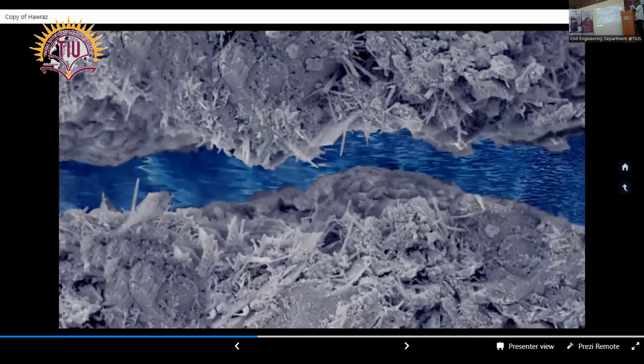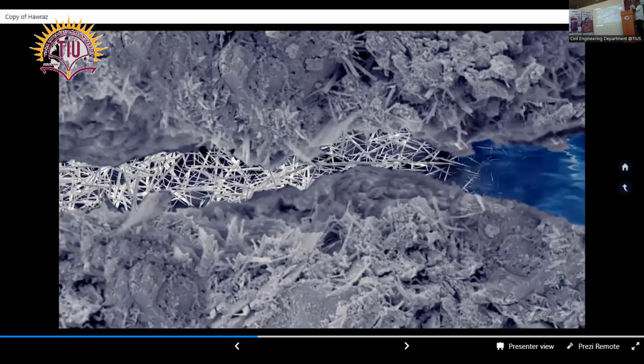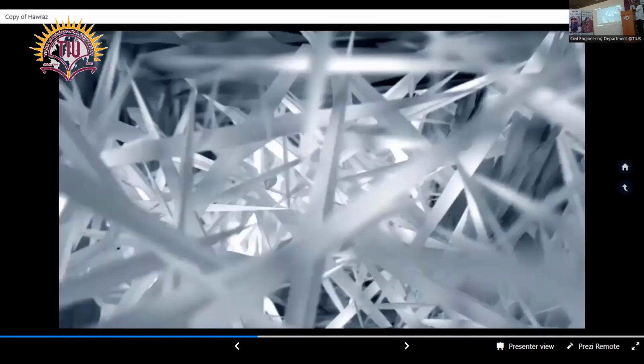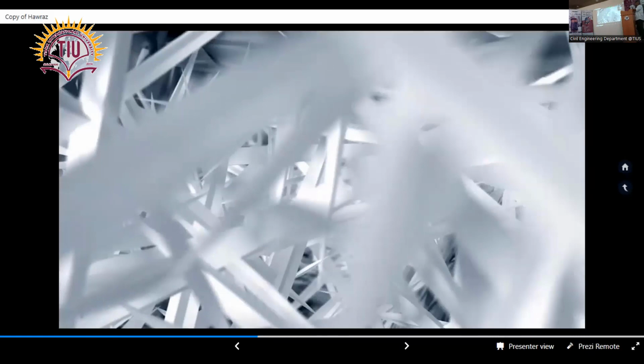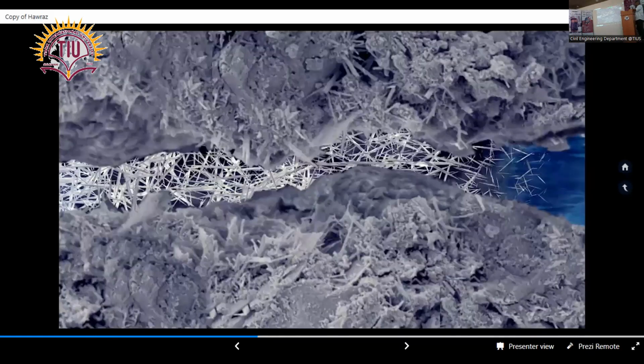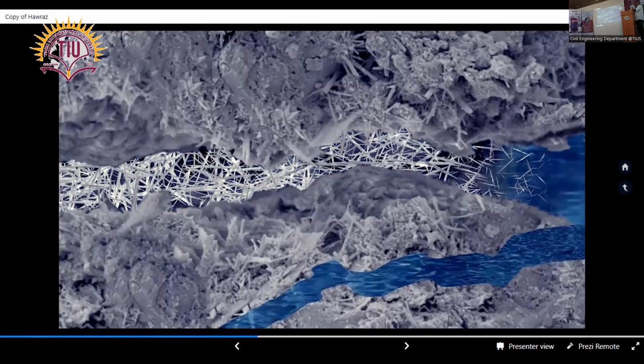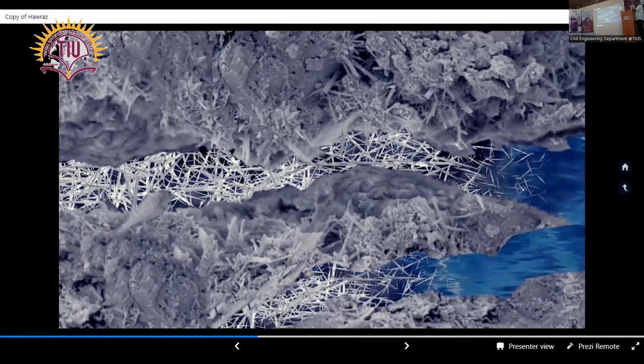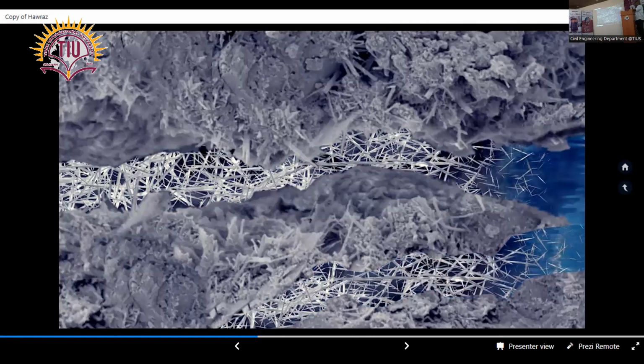Once inside the concrete, the Penetron components react with water, calcium hydroxide, and aluminum, as well as various other metal oxides and salts contained in the concrete, moving through the capillaries. The crystalline formation that ensues as a result of this reaction prevents water from moving through, but still allows air to pass, thus avoiding vapor pressure building up inside the concrete. If new cracks appear throughout the life of the concrete, Penetron crystals will appear in these cracks as well, preventing water from finding new ways to get through. When no more water is present inside the crack, the Penetron crystals lie dormant, but as soon as water reappears, crystalline growth is resumed.